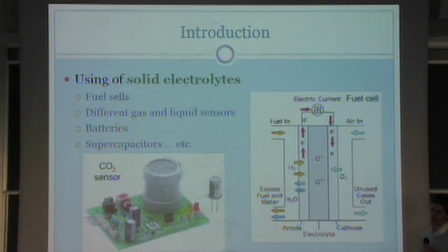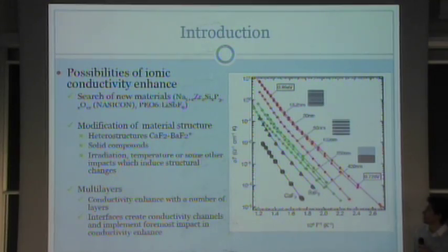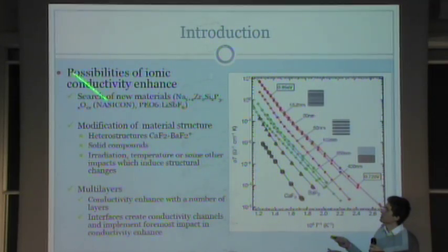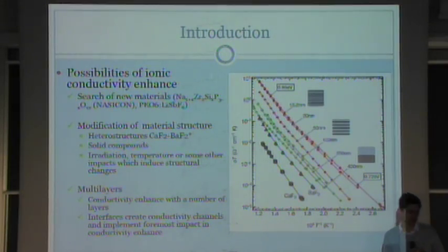If you substitute liquid electrolytes with solid electrolytes, it can solve these problems, but for example, as you can see here, there are some examples of using solid electrolytes nowadays, but we can't apply it to overall industry applications because there is quite a low value of ionic conductivity, so we can't use them without heating. How we can enhance ionic conductivity? There are actually a few ways. The most straight way to enhance the conductivity is to simply search new materials. Look for it, but it's actually quite a large topic. A lot of people are doing it, and it's quite hard to compete with a huge industry in this field. Another possibility is to modify ionic conductor structure.